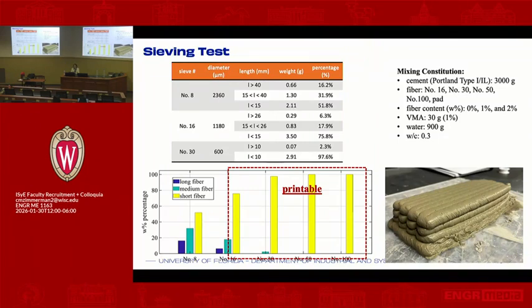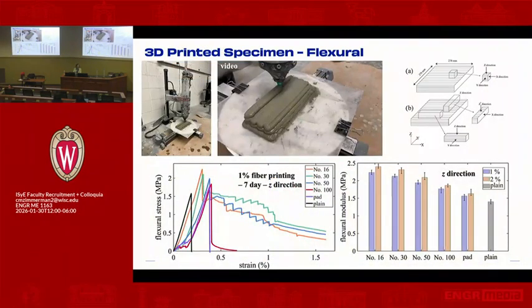So what you can see here is that there is a region where, depending on the size of the fibers, you're not going to be able to print much, categorized there by the fiber diameter. And if you're in the larger region, you're going to see a lot of clogging. That sweet spot there, sieve number 16, seemed to provide us the better outcomes when it came to printing, and the length was important as well. So 16 was one of the better ones. Fiber content went all the way to 1%, 2%, and we were able to do that. And I'll show you in the next slide what it will look like.